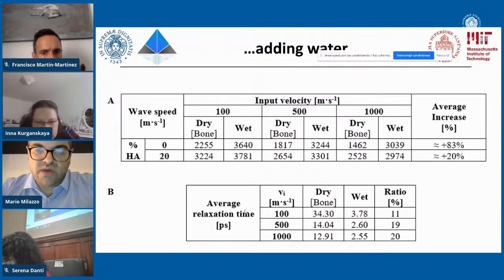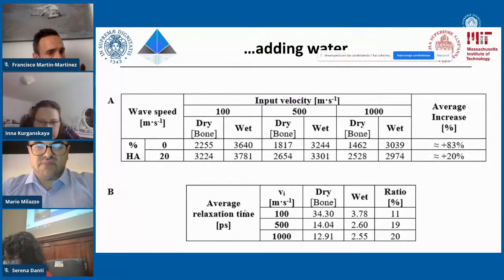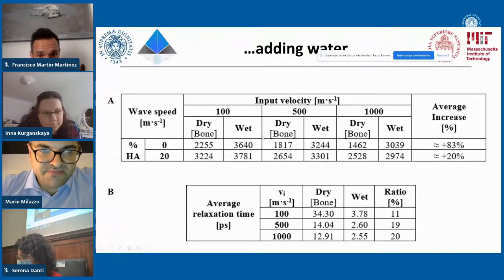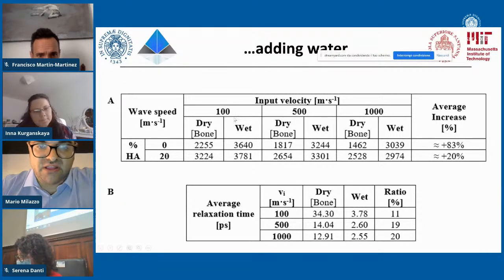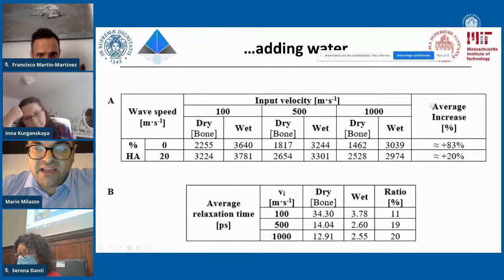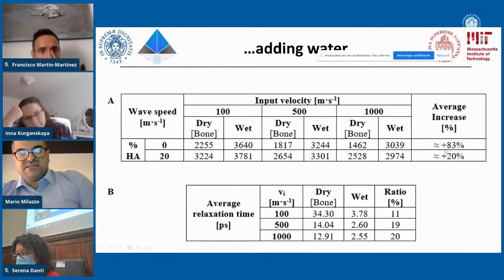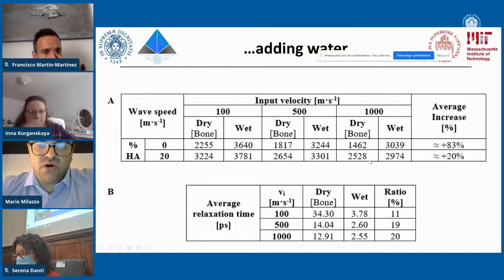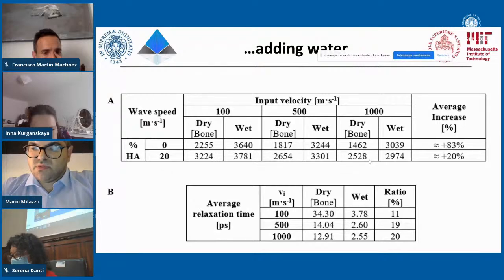As for the longitudinal waves, I'm just showing these tables, but what I want to show you is the difference between the wave speed in case of the dry structure and the wet structure. We have an average, a significant increase of the wave speed when we add water. So water is enhancing wave transmission, energy transmission, but at the same time is enhancing the dissipative behavior also along the main axis of the collagen fibril. And we can see that there's a ratio of between 10% and 20% between the dry and the wet structures.